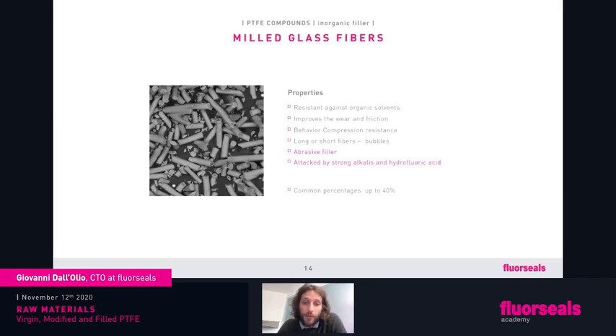The behavior on compression is really improved compared to the virgin PTFE, basically because the deformation under load is reduced. So when we apply the load, the fiber will help the PTFE matrix not to slip, and so we will have a better compression resistance.